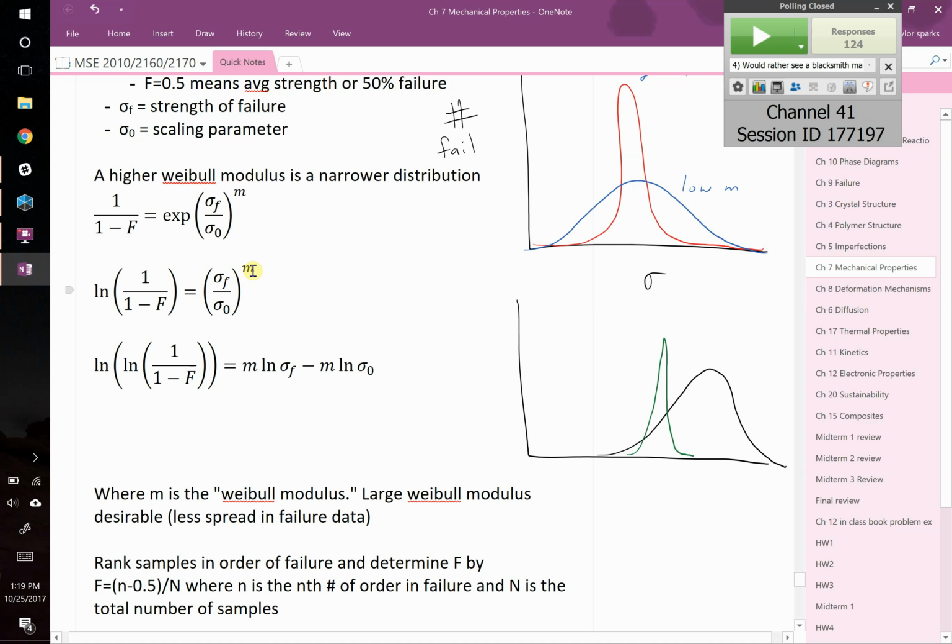Okay. So from those equations of a line, all I have to do is look and say, okay, y equals 4.5742x minus 27.011. Therefore, let me actually do this. In one of our samples, m equals 4.572, right? In the other sample, m equals 2.623. Okay? That's our Weibull modulus for these 2 different materials. So from that, now we can ask ourselves really interesting questions.